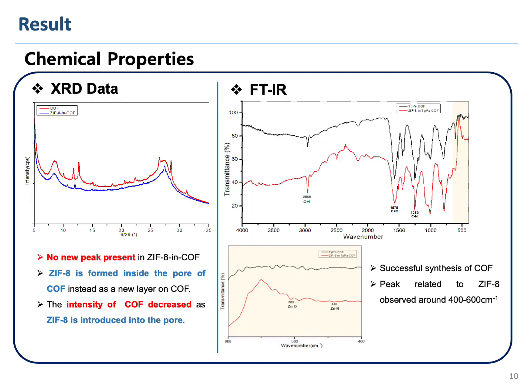Next is the chemical properties. From this XRD data, we can observe that there is no new peak present in ZIF-8 in COF. We can know that ZIF-8 is formed inside the pore of COF instead of as a new layer on COF. The intensity of COF decreases as ZIF-8 is introduced into the pore. Next is the FTIR data. We can see from this data the successful synthesis of COF. And from the enlarged image, we can confirm that there are peaks related to ZIF-8, observed around 400 to 600 wave number, which confirms the successful synthesis of ZIF-8 in COF.